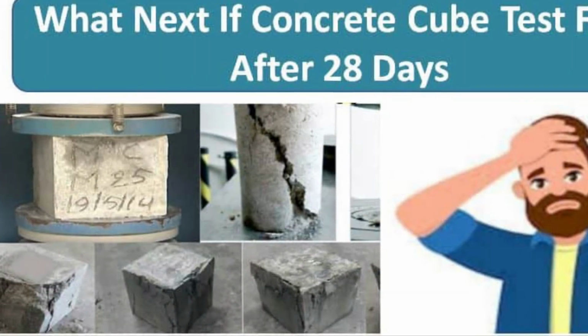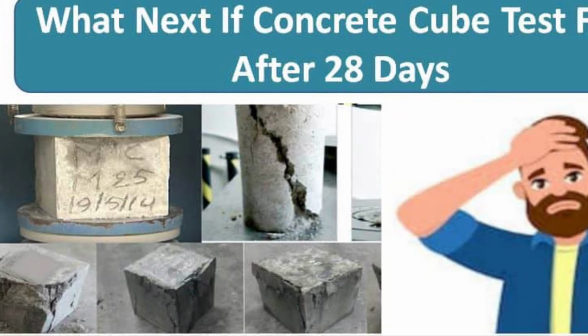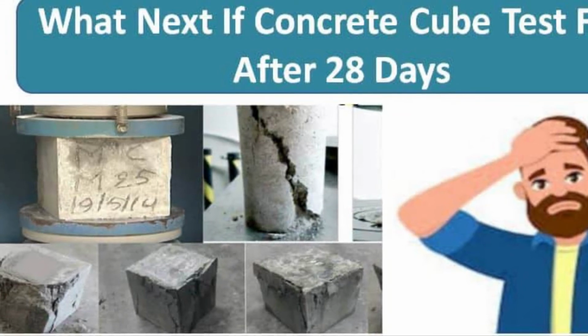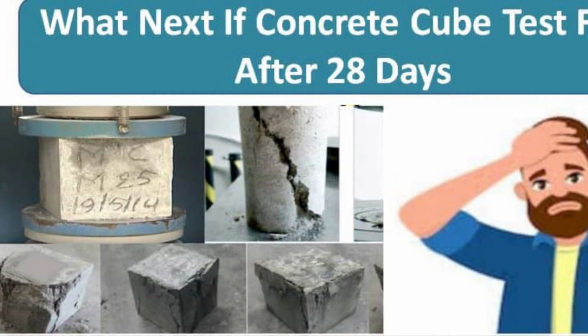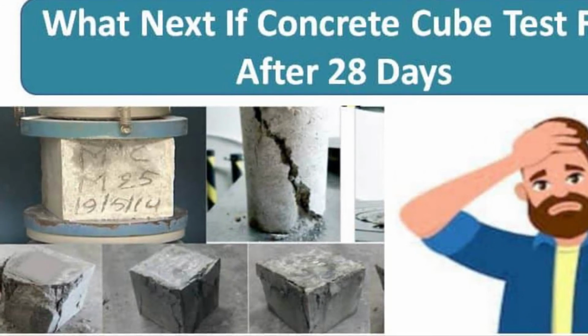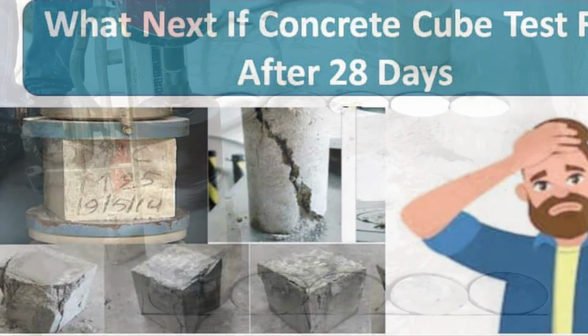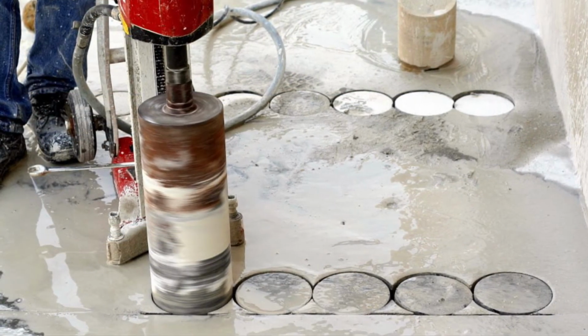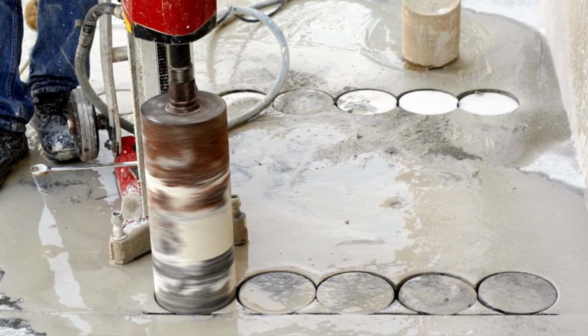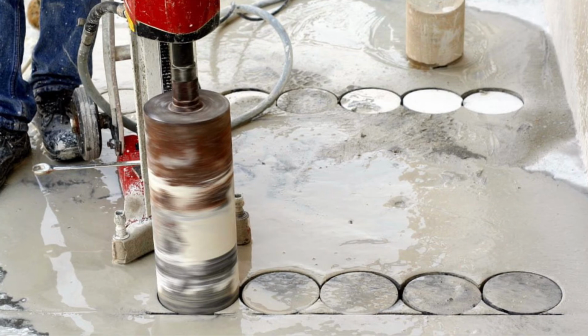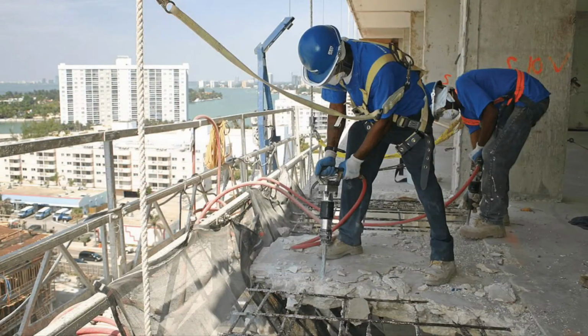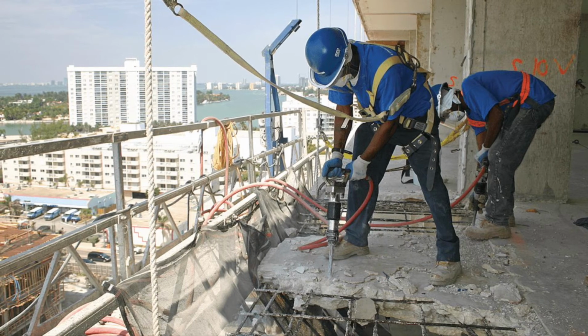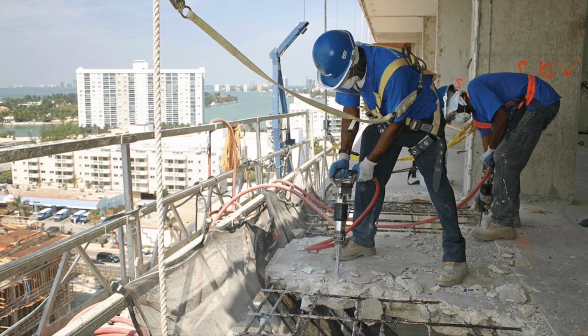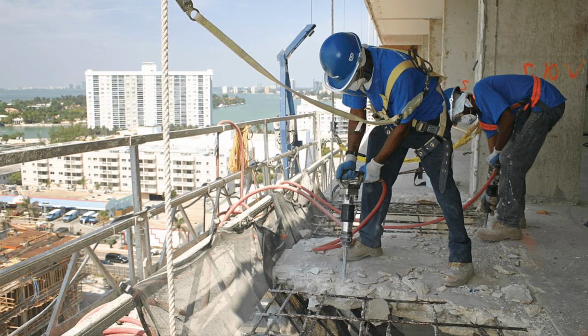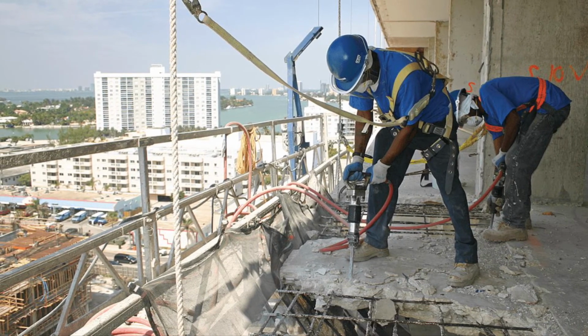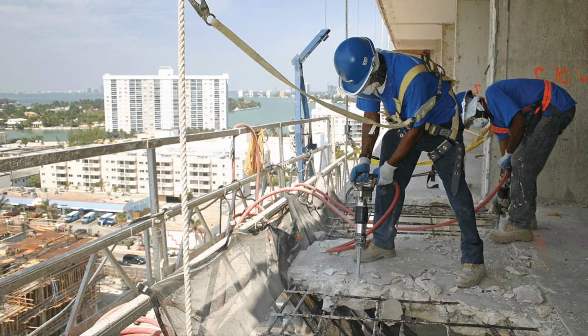During the testing phase, if the concrete test cylinder samples end up resulting in failure, engineers will begin to assess the possible causes. Failure of samples could be anywhere from the initial casting of the cylinders on site to improper curing conditions or improper handling of the samples during testing. While this is going on, concrete cores will also be drilled from the forms on the site and tested again. If these fail as well, the contractor may be required to remove all concrete from the site and start again. Not only will this cost the contractor to remove it, but it will also impact the critical path of the project by waiting for the concrete batch plants to mix again, transport, and run tests one more time before building.